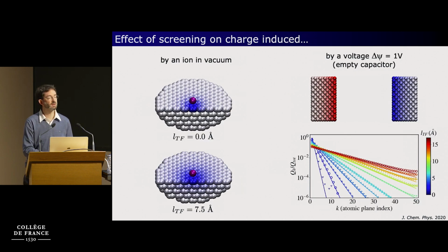So what is the effect of the Thomas-Fermi length on the charge induced here by a lithium ion on a graphite electrode? The color indicates the charge distribution. The darker color is a high local charge, and it fades away as you go away from the ion.